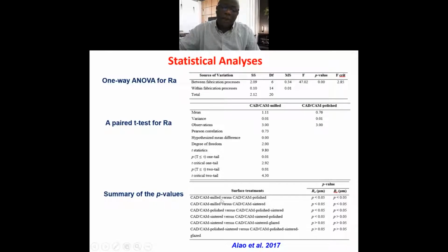You can see for the CAD-CAM milled versus CAD-CAM polished, for the two surfaces, the polishing really affected the milling process. The same thing also for sintering. Here, the sintering process after polishing significantly reduces the surface roughness. However, glazing after sintering does not reduce the surface roughness. So the two are not affected.